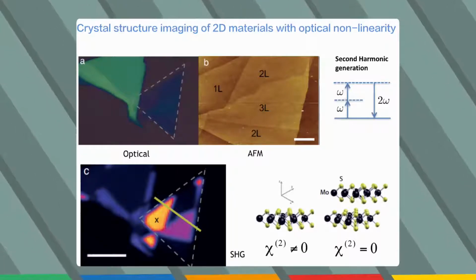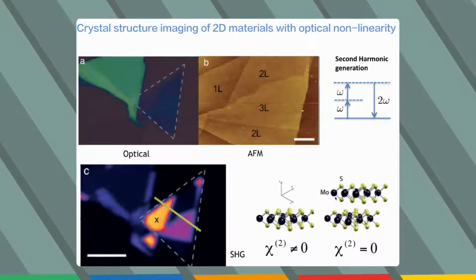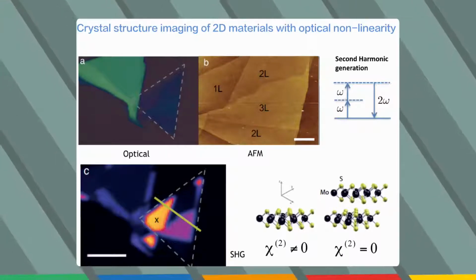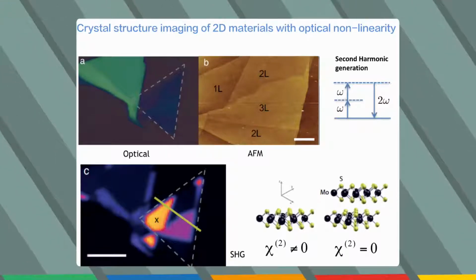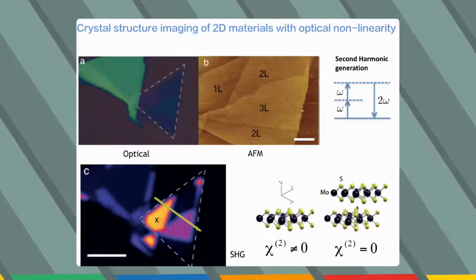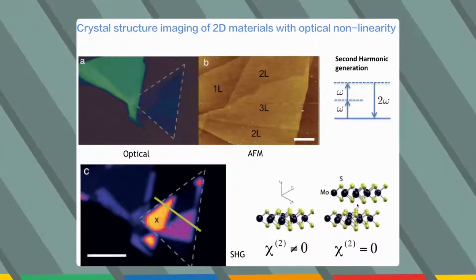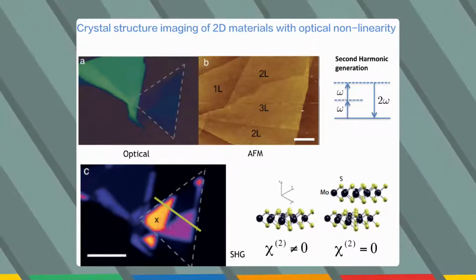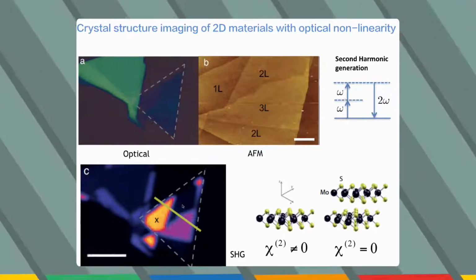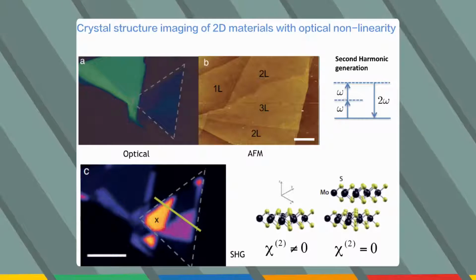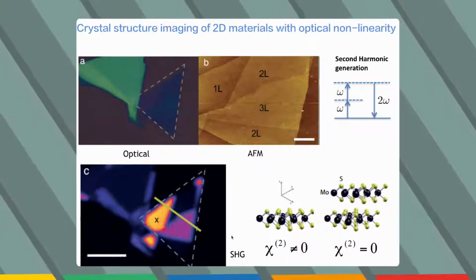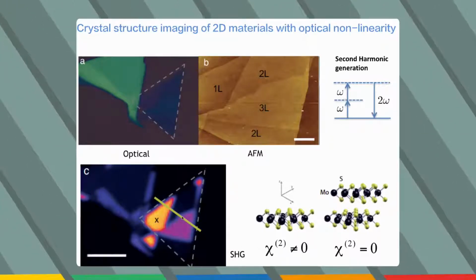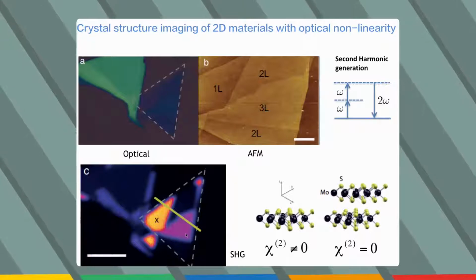So if you look at the MoS2 crystal, we see that when we have a bilayer, we have an inversion symmetry operation just in between the layers. So in this case, the Chi2 is 0, so we don't see any second harmonic. We only see it for an odd number of layers, so 1 layer and 3 layers in this case.